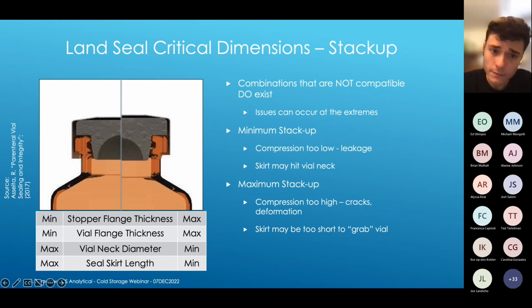Considering that land seal, similar concept, we're looking at minimums and maximums, and we're looking at the combinations of these minimums and maximums and their impact on integrity. So as an example, if we take the minimum stopper flange thickness, the thinnest stopper flange within dimensional tolerance range, and the minimum vial flange thickness, smallest distance from here to here, and we use that with the maximum skirt length, so the maximum allowable within tolerance aluminum crimp seal skirt length. Does this package system seal? And if it seals, does it seal well?